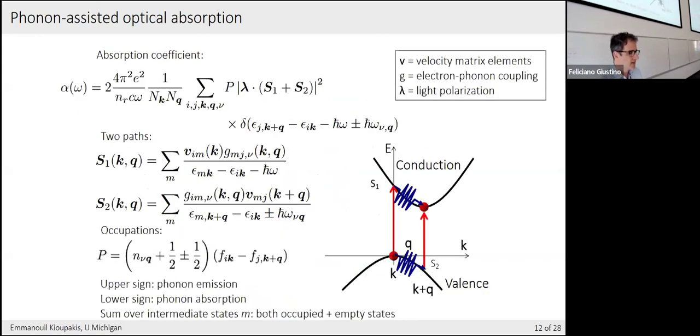All right. So following the same steps as before, we can transition from this fundamental equation from the rate to the absorption coefficient for materials. Okay. So this is the end result. If you want to find the absorption coefficient for phonon-assisted optics, now you need the following elements. Again, we have this prefactor, which is again optical constants. We have a delta function to conserve energy. And now we have to account for the fact that your initial electron at state I absorbs the photon and also absorbs or emits a phonon and ends up in state J. Okay, so the phonon also enters the energy conservation.